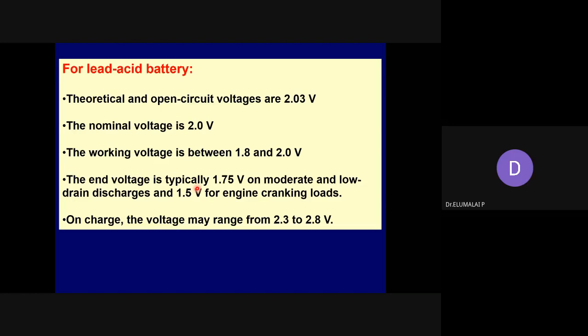So that's why I'm telling you, the depth of discharge for the lead acid battery is maximum 80%. So it means if the full voltage is 2 volts, you should be able to discharge up to 1.8. 20% of the charge should always be kept in the lead acid battery. Then only it can be used efficiently. Repeatedly, several times you can do charging and discharging. If you do DOD 100%, the life of the battery will go down or the battery will not function properly. Full potential, full battery performance, is not possible to get.